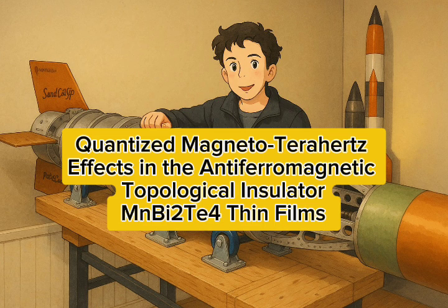And the calculated Hall conductance for the 7SL film at high field? Also very close to quantization. Under 6 Tesla at 0.4 terahertz, they calculated GHC to be around 0.86 e²/h for the 7SL film. Again, very near that 1 e²/h value. So it seems consistent across both even and odd layer counts once you push it into the ferromagnetic state with a strong field. That's the takeaway.